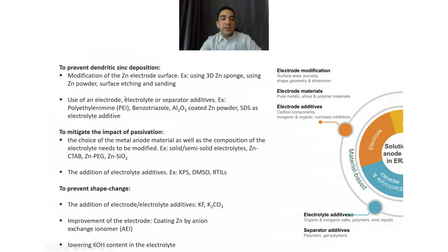Next is how to mitigate the impact of passivation. So you can either choose a different metal for anode material, or change the composition of the electrolyte. For example, you can use semi-solid electrolyte instead, or use zinc polyethylene glycol, or silicon oxide, and many other examples are available in the literature focusing on reducing the impact of passivation. Also, you can use additives to the electrolyte like potassium persulfate, DMSO, or even room temperature ionic liquids can be helpful.